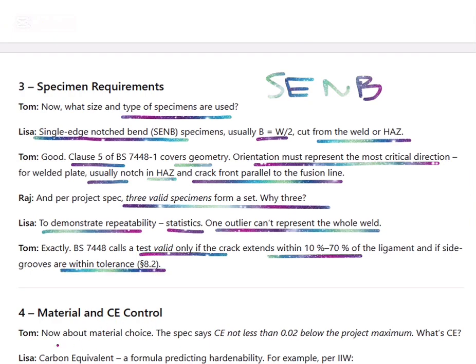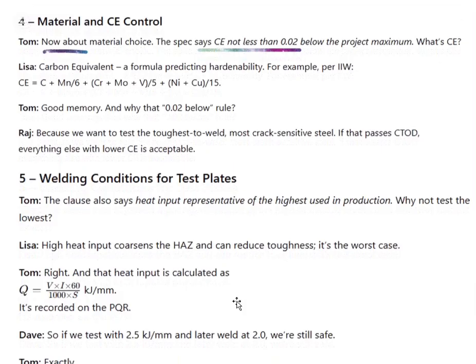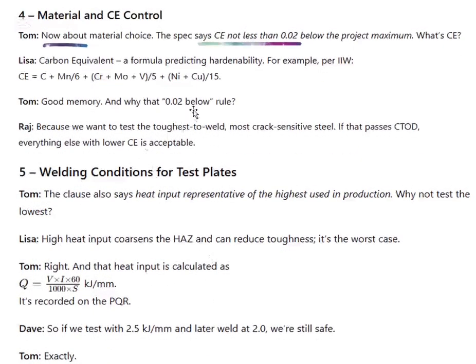Material control. Now the material choice. The spec says CE not less than 0.02 below the project maximum. What is CE? That's the carbon equivalent, a formula predicting hardenability. Good memory. And why that 0.02 below rule? Because we want to test the toughest to weld, most crack sensitive steel. If that passes CTOD, everything else with lower CE is acceptable.